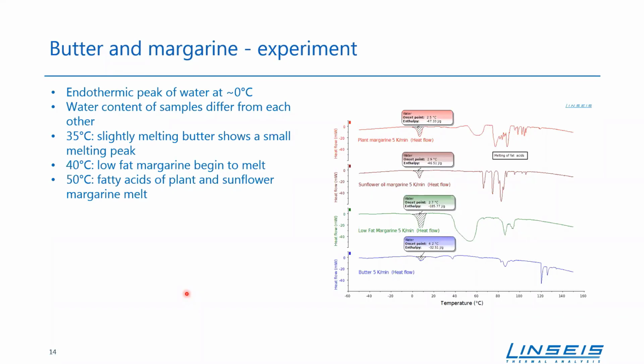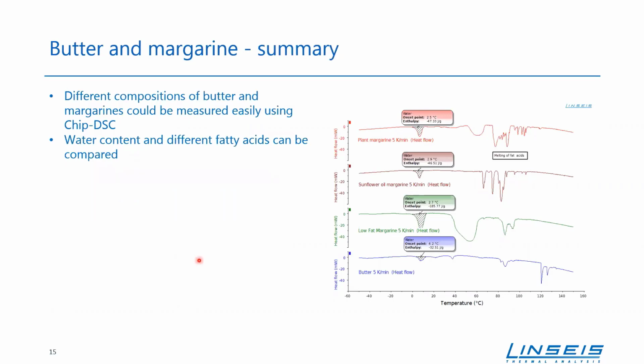There are also slight melting peaks of butter at 35 degrees, and at 40 degrees the low-fat margarine will begin to melt, and the fatty acids of plant and sunflower margarine melt at around 50 degrees. So this is what we received in this measurement. Sorry, this was too fast. To sum it up, it's really possible to distinguish the different samples, the margarines and butter, through their composition. It's also possible to figure out the water content of our sample and to get to know what about the fatty acids in the sample itself.